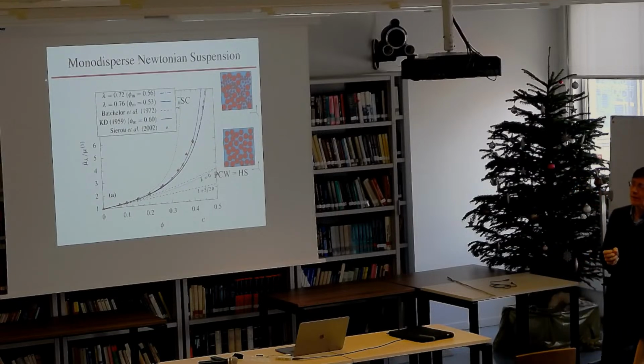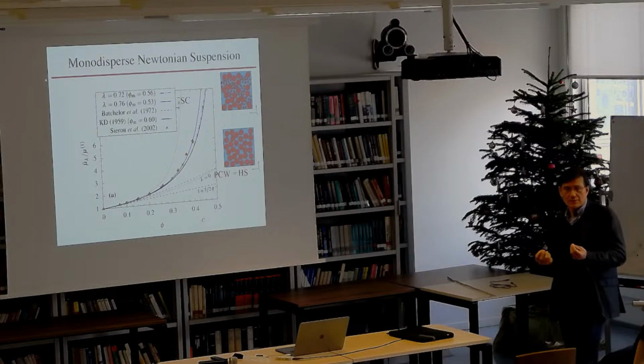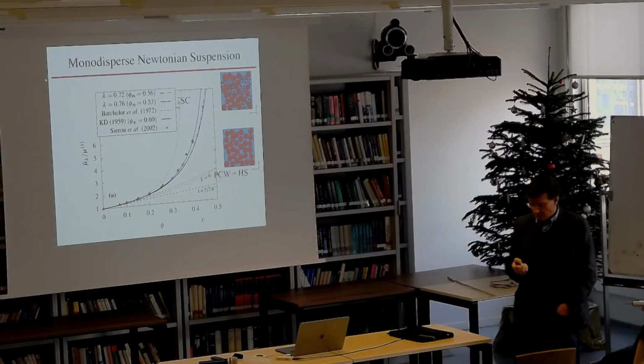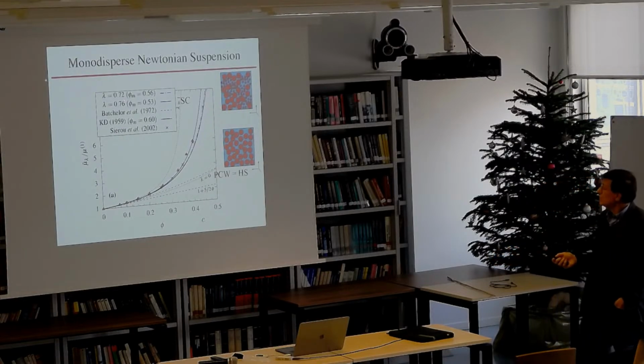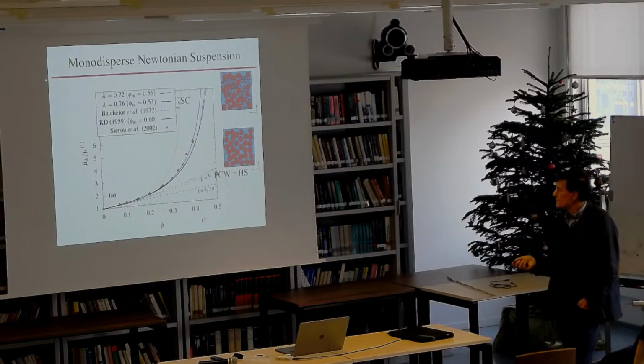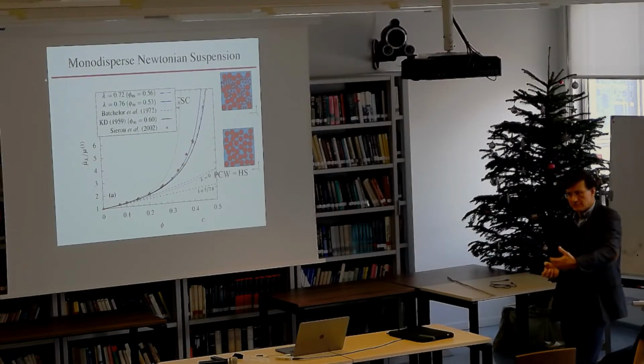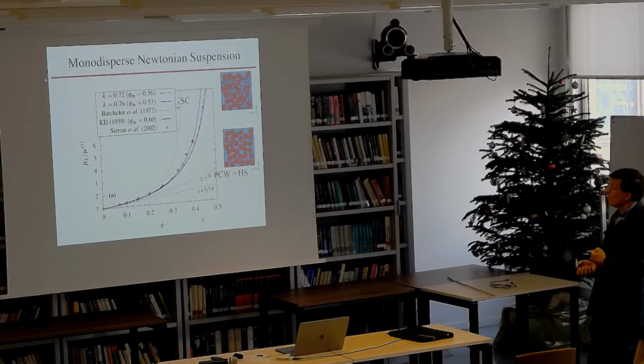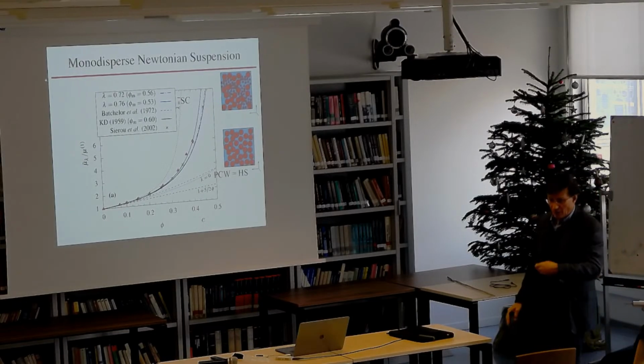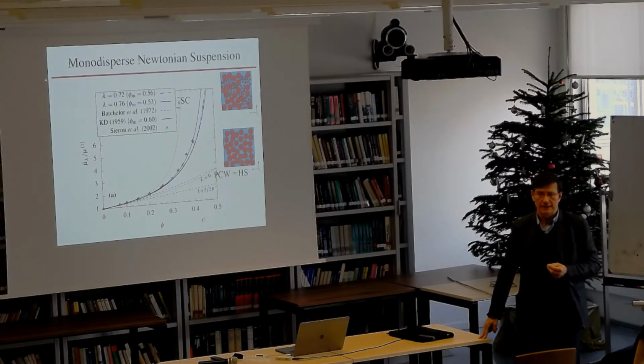So we want to find a way to get this empirical parameter from something about the microstructure. The 0.72 we obtained by looking at this result here in dashed line, which comes from an exact asymptotic expansion, Batchelor and co-workers, where they tried to go beyond the Eshelby dilute estimate to incorporate terms of order volume fraction squared. So you can get an estimate for this term, and you find that it depends on the radial part of the pair correlation function.